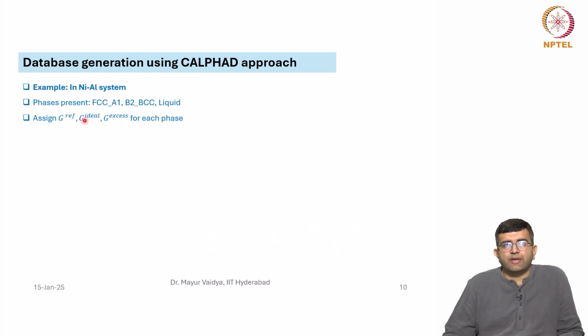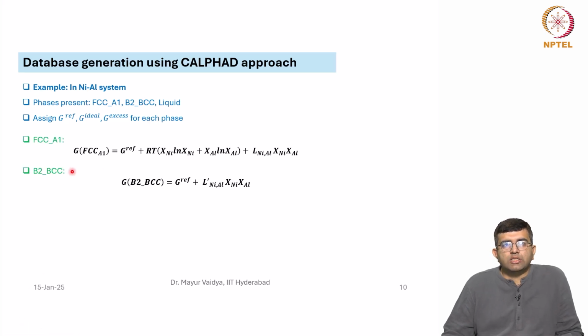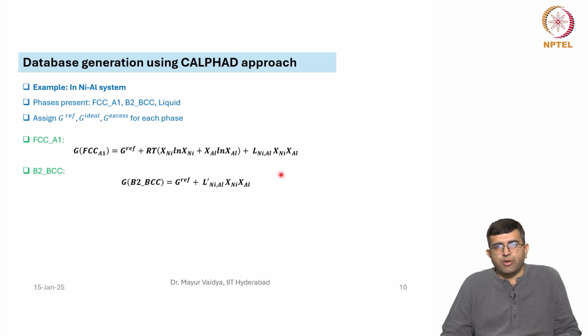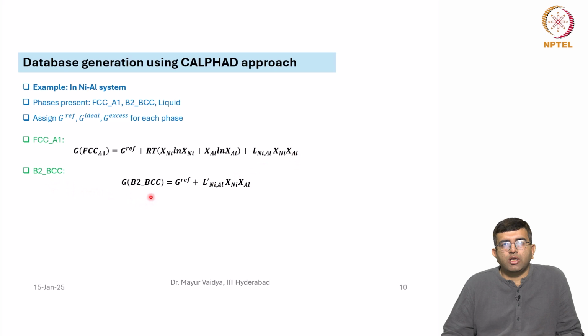So, for example, in a Ni-Al system, let us say the phases present are FCC, B2 and liquid. This is just for simplicity. There are more phases in the Ni-Al system. So, for example, for FCC A1, the free energy can be written as G ref plus RT [x_Ni ln x_Ni plus x_Al ln x_Al] plus this parameter L_NiAl into x_Ni x_Al. This is a very simple description. Okay. So, in this, this is an excess term if you can call it. Then for the B2, you can write G of B2 BCC is G ref plus L' NiAl x_Ni x_Al.